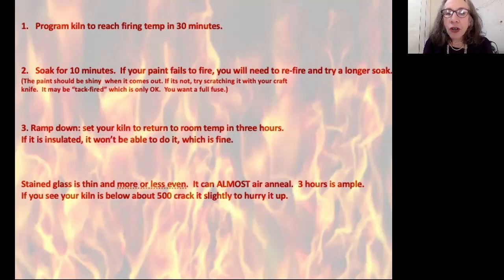You can go up and cool down fairly fast. Just maybe don't open the kiln door when it's between 1,000 degrees Fahrenheit and 500, just to be on the super safe side. Some people like to open the kiln when it's at temperature to see if the paint has become shiny, but you won't need to do that when you know what temperature your kiln fires at.